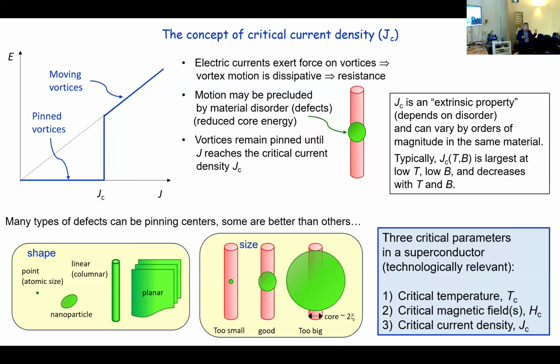These defects, which are non-superconducting regions, attract the core of the vortex. When the vortex sits in there, the energy of the core is decreased, and so that acts as a potential energy well. Then you need to apply a finite current in order to move the vortex out of that. The vortex is pinned. And that is the whole story.